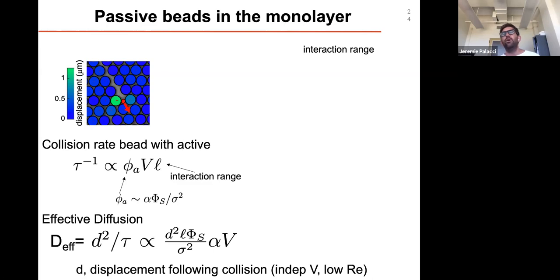Another thing you have to think about when you do the experiment is that it's actually not 2D, it's quasi 2D, they are spheres. So if you take a very small active particle, there's actually a lot of space below the belt of the large passive ones to travel without touching anyone. So you need your active particles to be large enough so that they still push the passive ones when moving around. And we have this caveat that if we go too big, then we need to form disclinations and they just don't happen. Does it answer your question?